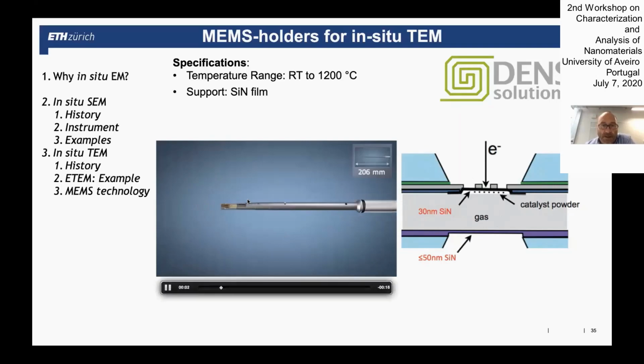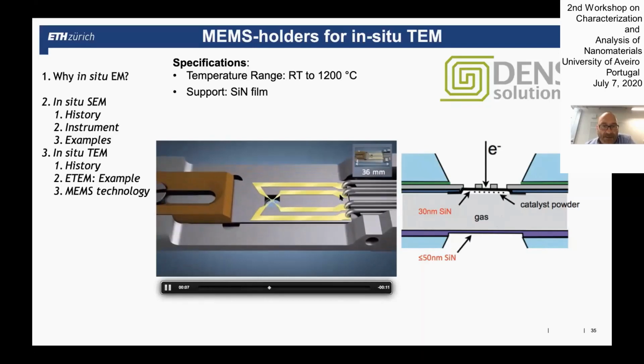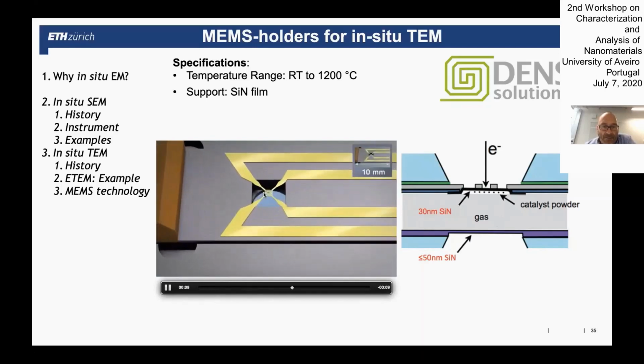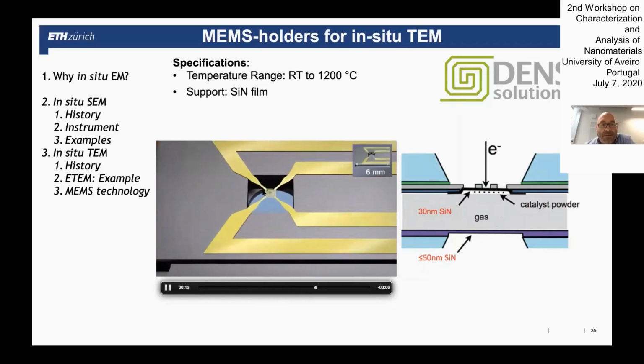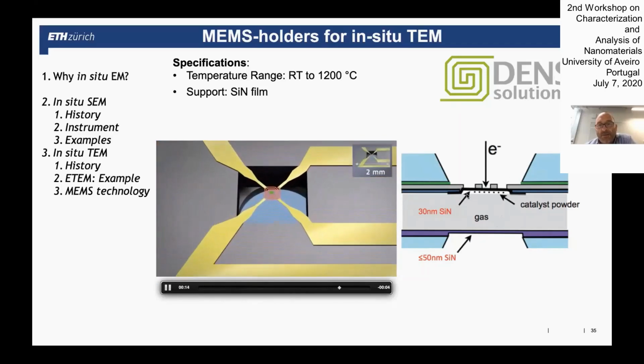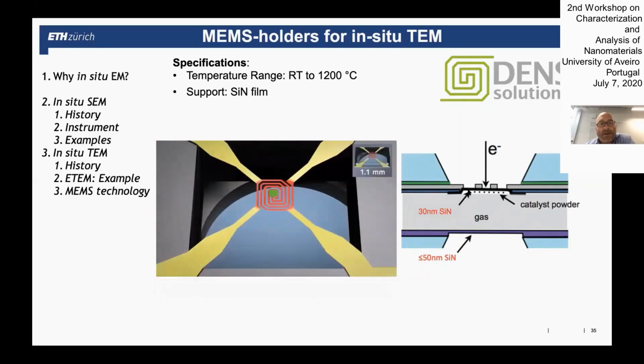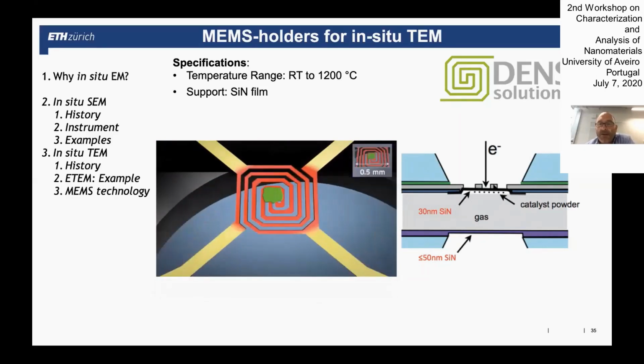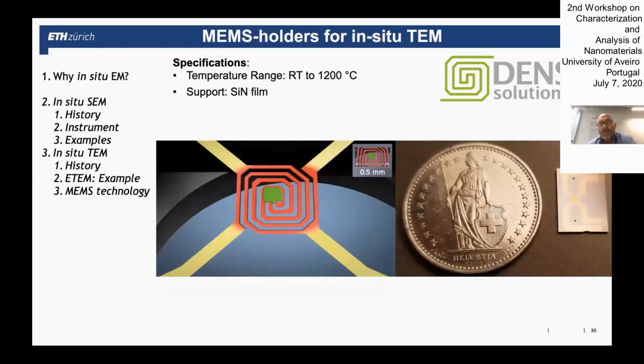So this is a TEM sample holder. In the very front, in this case, there's a heating chip. So you have the current going through the spirals, and you can heat up your sample. And all this is actually microfabricated onto these windows. So it's really a micro electromechanical device, a MEMS device, that allows you to build your little reactor. And I have here just as a size comparison such a heating chip where this spiral is contacted by 4 points. You can apply voltage, send the current through, and measure the resistivity so you can get feedback about the temperature. So this is such a spiral, as you see here.